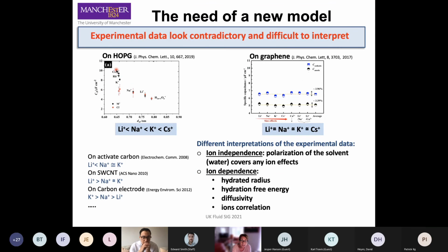Experimentally, as I was saying, you can see adsorption of ions on the surface, but the experimental data are very confusing. I mean, you can really find a lot of different results. So for example, this is an example of electrochemical measurements. This is the specific capacitance, which is a value that is directly related to the amount of ions you adsorb on the surface. And this experiment has been performed on these highly ordered pyrolytic graphitic surfaces, so very atomically smooth surfaces, but it's still graphite, so several layers.